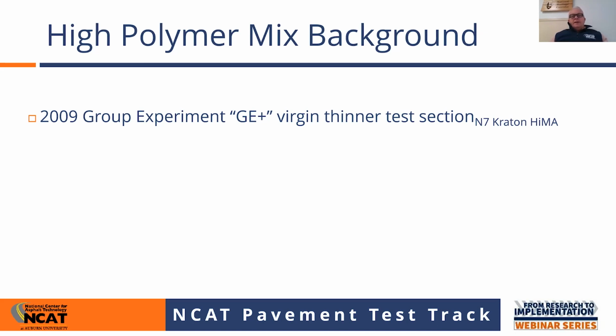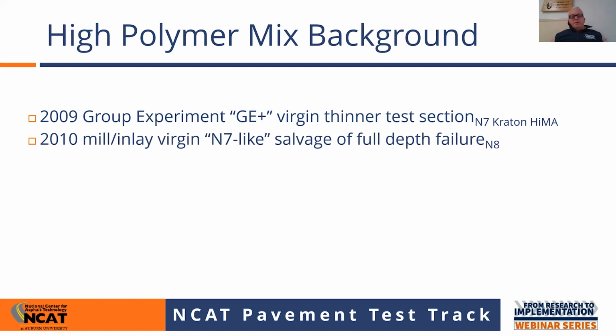So the group experiment had 5-inch, 7-inch, and 9-inch pavements, and the Kraton HiMA binder funded test section really was intended to show, hey, we can build these pavements thinner and get thicker pavement performance out of them. That experiment did so well that we had a totally different test section that had a really high PI clay as a subgrade that was not intentionally designed to be not thick enough. So we had a full depth failure in it, and we ended up doing an N7-like mill and inlay salvage to convert a failed structure into a perpetual pavement by focusing on inlaying what we proved would appear to be perpetual in section N7.